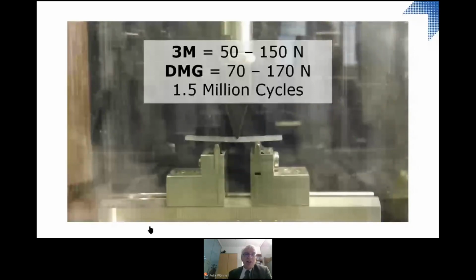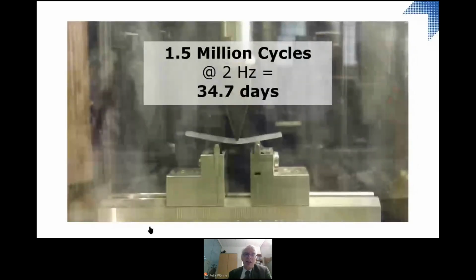So we have this sample being loaded and unloaded from 70 to 170 and back every 2 seconds. So that's what we call a cycle. 2 hertz, 1.5 million cycles. That means that one single measurement for one particular sample lasts 34.7 days, which is more than a month. So it's a pretty slow process coming to the opinion that, yes, this is going to last.